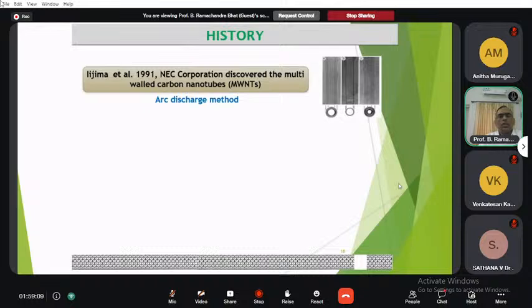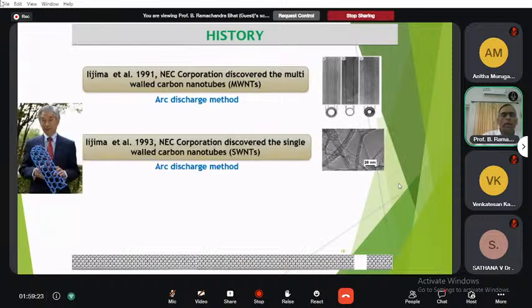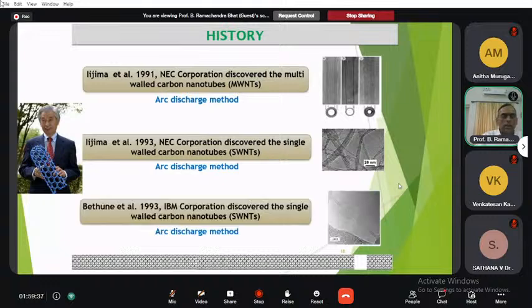Now, coming to the history of the carbon nanotube, as I said, Sumio Iijima reported the carbon nanotube. This is a multi-wall carbon nanotube in 1991, and in 1993, again he reported a carbon nanotube synthesized through the arc discharge method, and in this case, it's a single-wall carbon nanotube. And the Bethune report in 1993 is again an arc discharge method. So you can see the STEM images of a single-wall carbon nanotube.